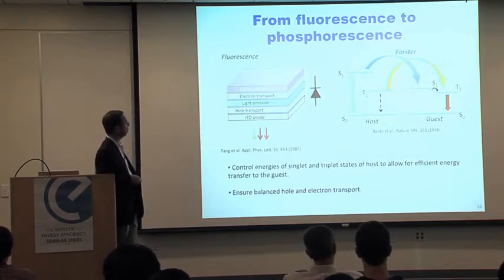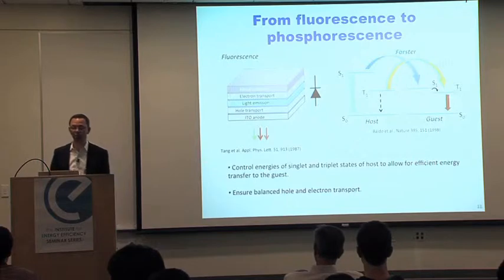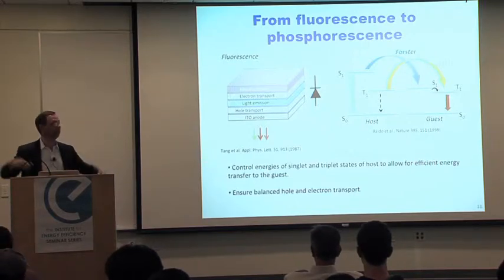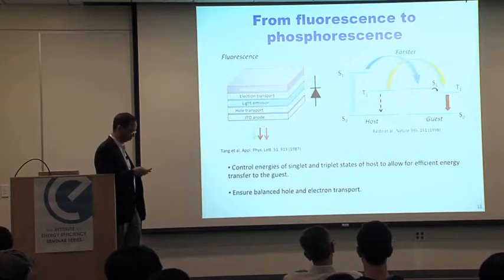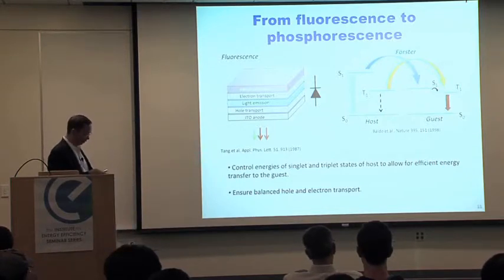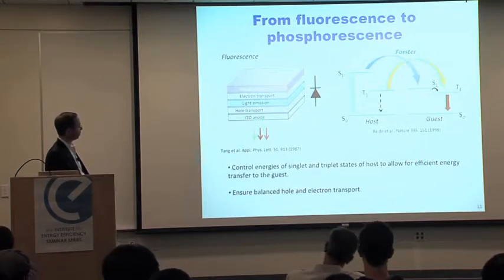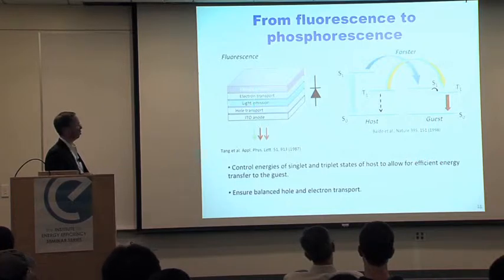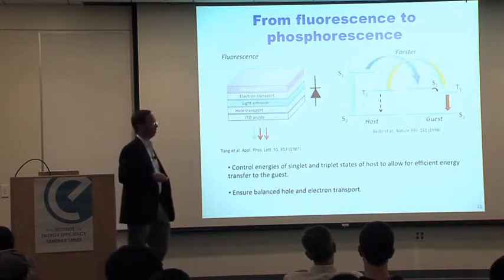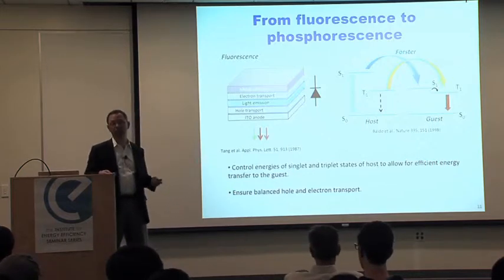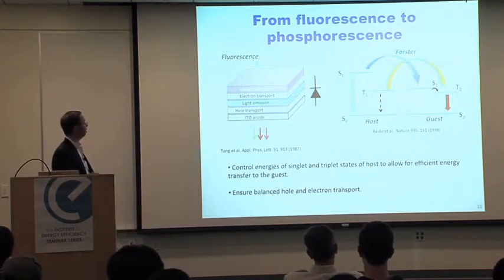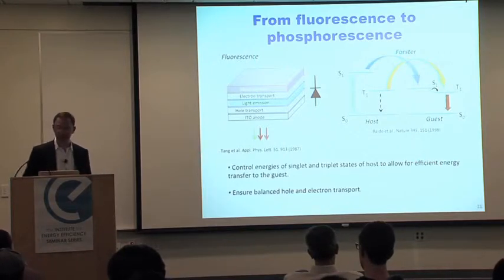Of course, the light that is emitted is also limited by how much light gets trapped into the structure by total internal reflection. So in a lot of these early devices, the emission takes place through that transparent electrode. And another problem with a lot of these structures is that usually for the cathode, in order to efficiently inject electrons into these organic semiconductors, you're using metals which have a low work function. And these metals are highly reactive. And so if that's on the top, you have to protect it very well with an encapsulation layer.